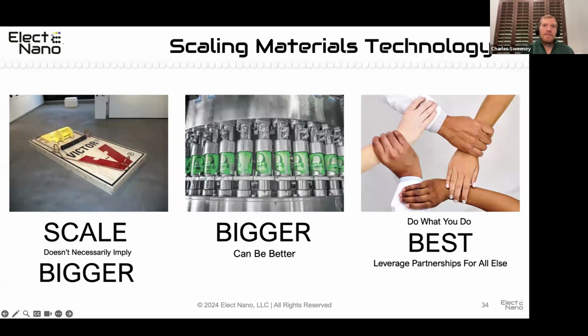That was, I think, the grad school scrappy way to try to make more filament and scale the process. But in reality, the only way that we actually ended up growing that technology at Ascentium was to switch over to an extrusion process, co-extruding a thin jacket, a sheath, on the outside of the filaments. And it made life so much easier, because then you don't have to wait for solvent to dry, and it doesn't mess up the coating. And it has new challenges, but they are much better challenges when your throughput is super high and you can really scale the technology. So scaling a lot of times means adapting and inventing new ways of accomplishing something at a larger scale.